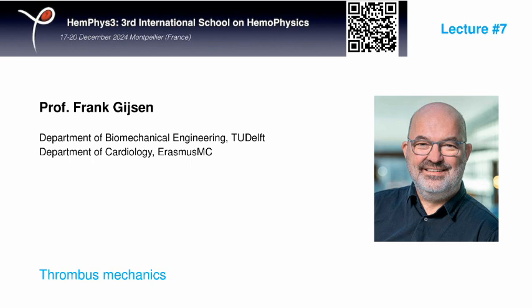I don't really regret it, but part of me regrets it nevertheless. We've adapted the protocol so that we could compare our findings against other preclinical studies that were done before. They subjected their samples to very high compressive strains. The effect of that high compressive strain is that you expel fluid, which is not surprising, from your sample. You can visually see that happens. Not all the fluid gets sucked back into the sample, so you have a different structure in the end.